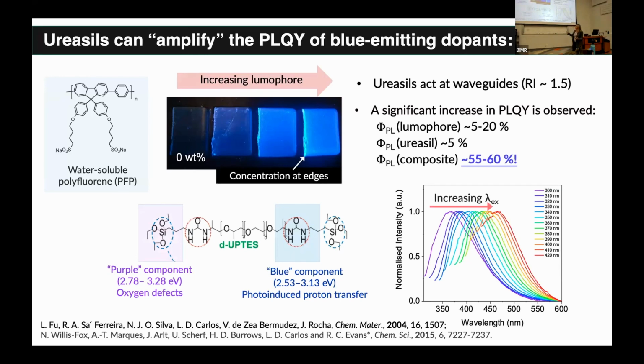I hinted at the fact that ureasils themselves are very weakly luminescent. This has previously been studied by Luís Carlos's group in Aveiro in Portugal. It's attributed to a defect emission based on the silica backbone and also a photo-induced proton transfer at the urea groups. But the quantum yield is quite low, 5%. Our conjugated polyelectrolyte is quite a weak emitter in solution, so you can only get about 20% in a good solvent. But when we put the two things together, we get this increase in the photoluminescence quantum yield up to 60%. So we have a material that is amplifying the emission of our blue light.